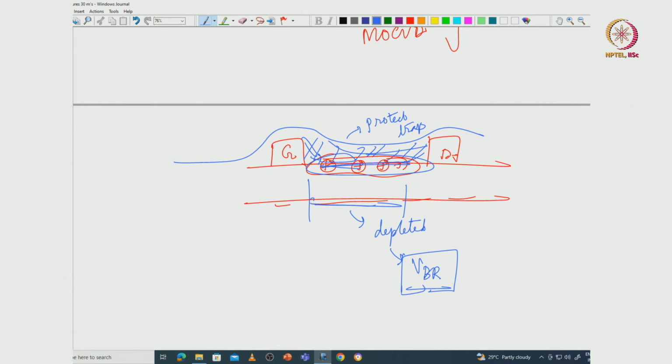So, if you passivate, what happens is that your surface traps cannot be neutralized by this gate injecting carriers, and so your device will respond faster. So, essentially if your cold fed condition look like that, then your drain lag also will be very low, because you're basically not allowing them to get neutralized as much. So, you will have less collapse, but the compromise, or the trade off that you have to make, is that the breakdown will be sacrificed, because this depletion region will also not extend as much,